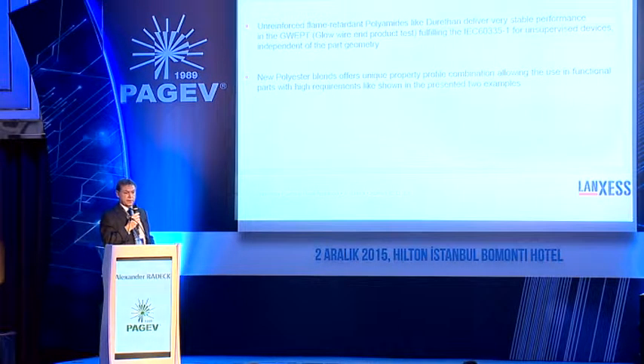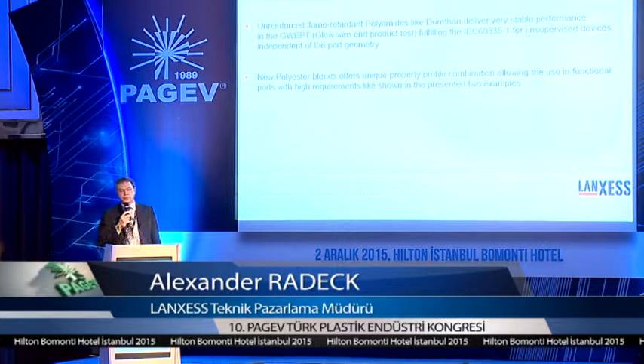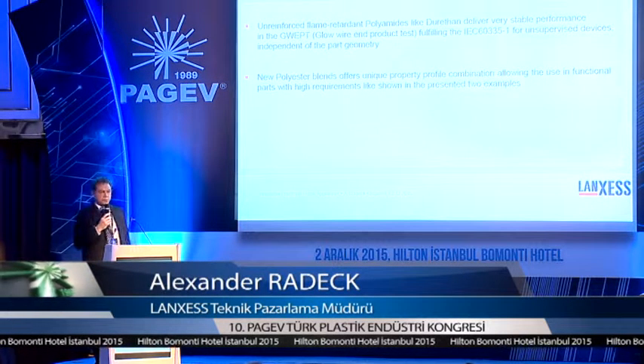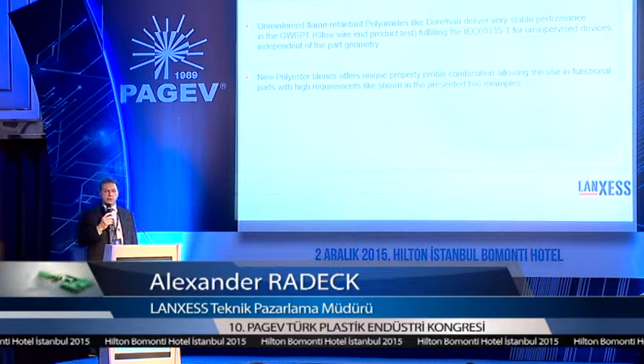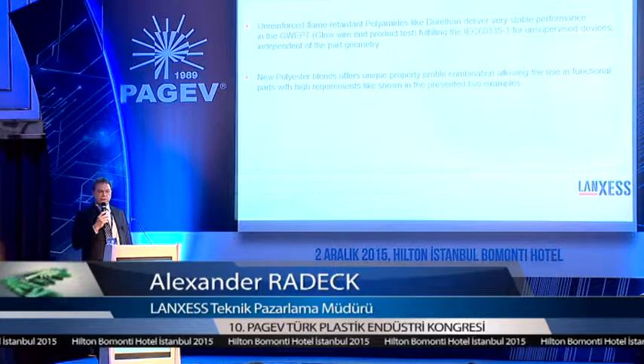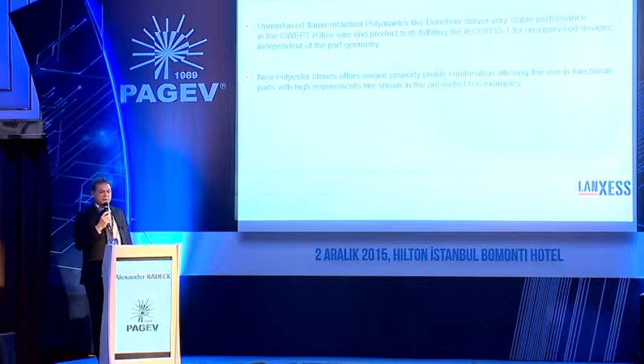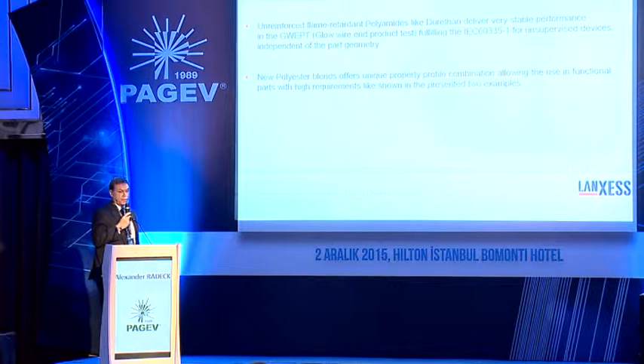Coming to the end, I have shown an example of an unreinforced flame retardant polyamide with a very good performance in the glow wire test performed on the finished part, and this independent of the part geometry. And that should give the part developer a lot of confidence at a very early stage of the part development. And I also showed some new polyester blends with a unique property profile, which allow use for functional parts with very high requirements, as I have shown in the two examples.